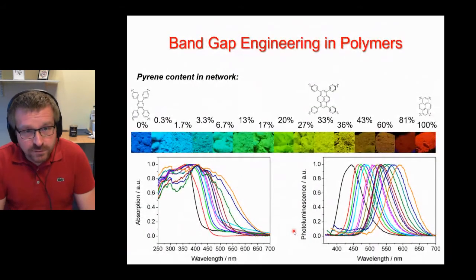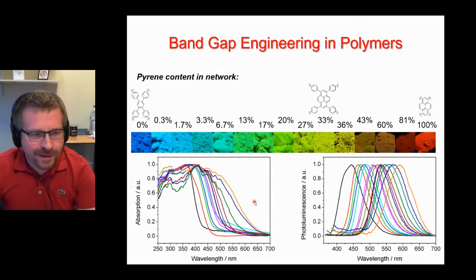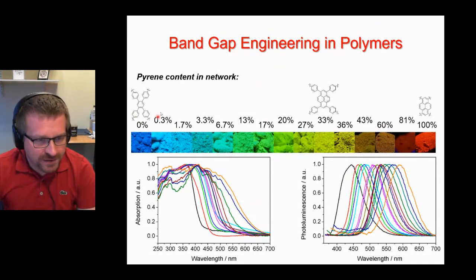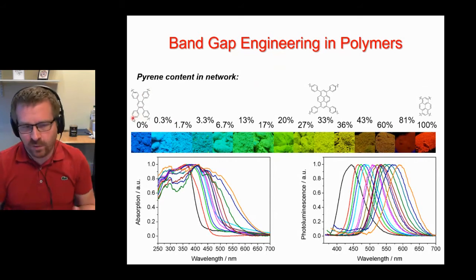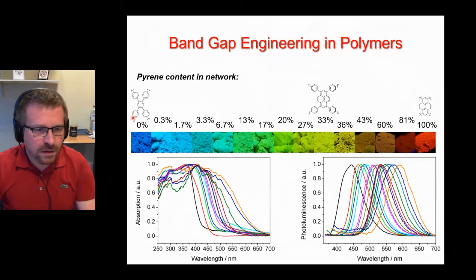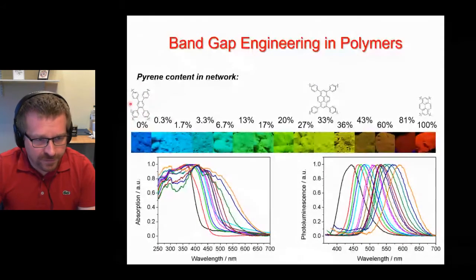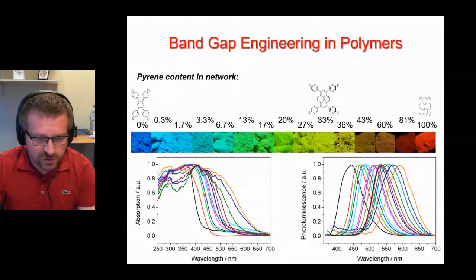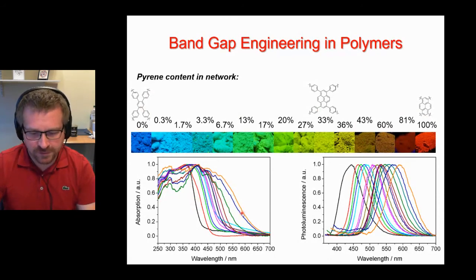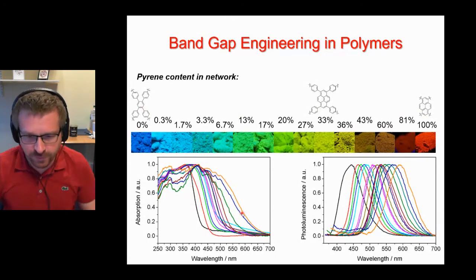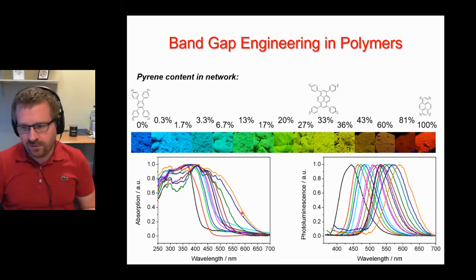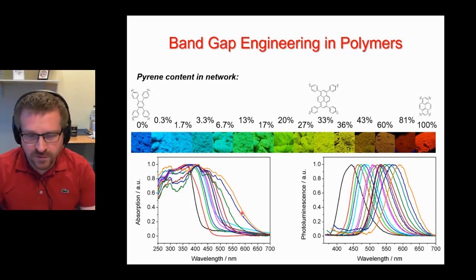This was really our starting point as well. We had some experience in making these conjugated microporous polymers, so they combine conjugation, but they also don't pack well in the solid states. They have internal porosity, and we had the idea with this material here, by incorporating more and more pyrene. As you go from the left to the right, you can see the colors change. We also shift the absorption onset from really in the blue more and more into the red, which shows the power of this approach. Really, just changing building blocks really changes the optical properties very efficiently.